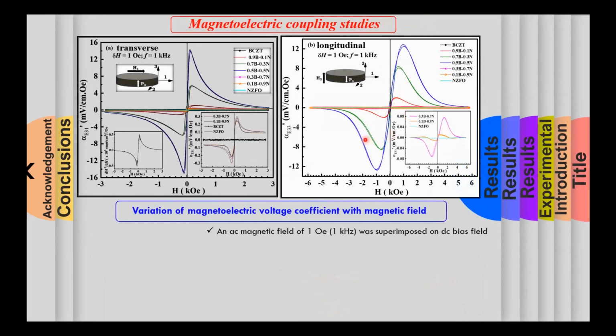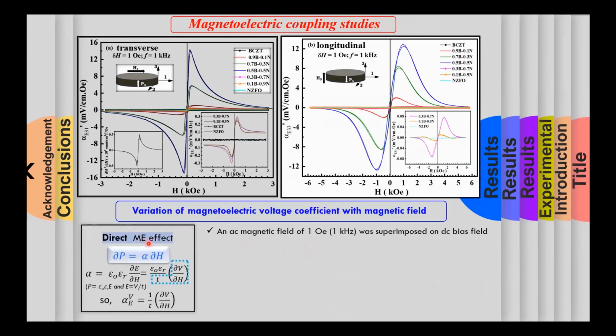by recording the electrical response to applied magnetic field, like I showed in one of my previous slides, the direct magnetoelectric effect. The samples were subjected to a biased magnetic field superimposed with an alternating magnetic field of 1 oersted at 1 kilohertz. Since polarization is related to electric field through permittivity, and since electric field is given by voltage upon thickness, the relation modifies into this relation.